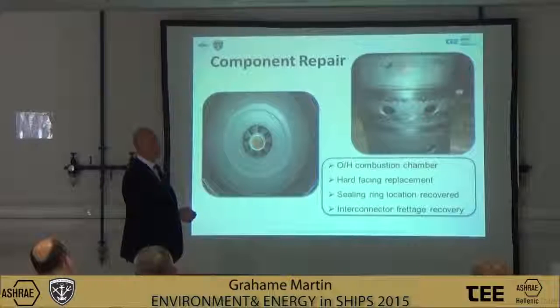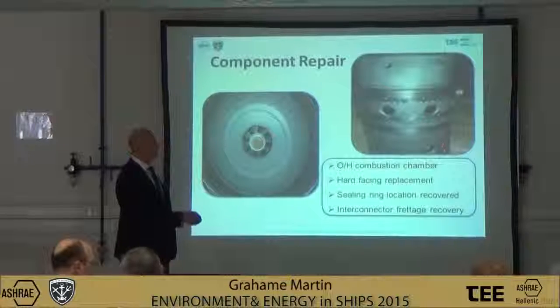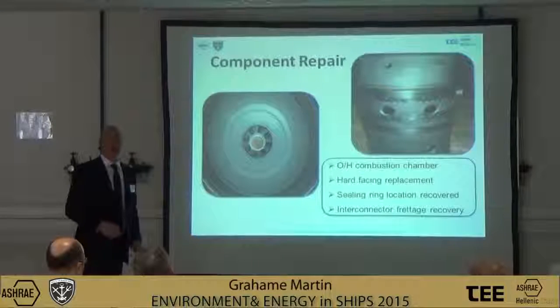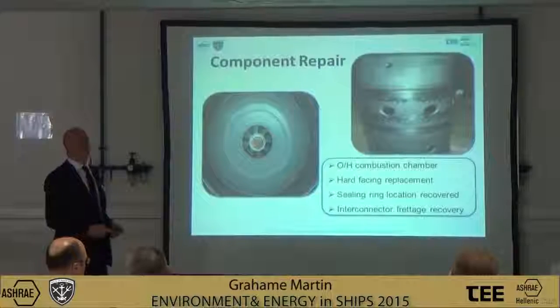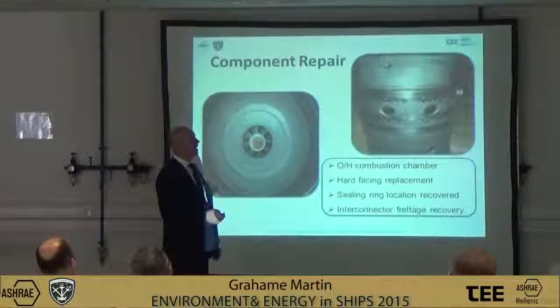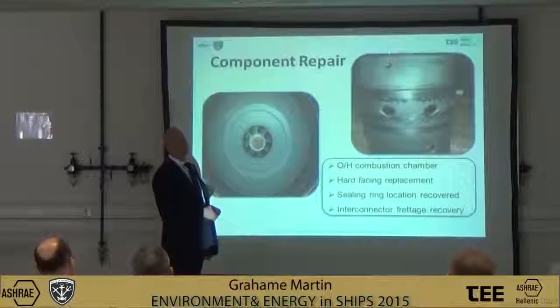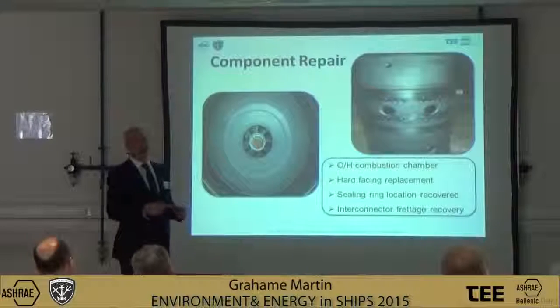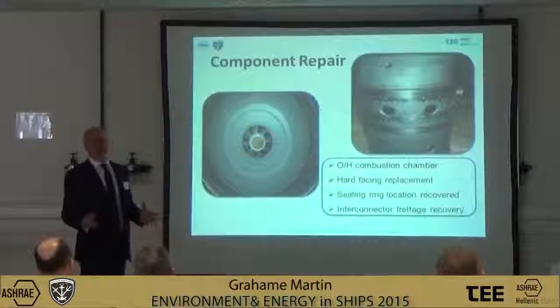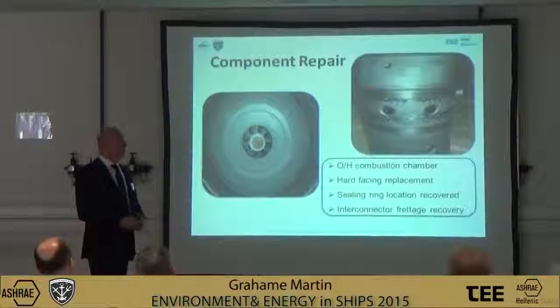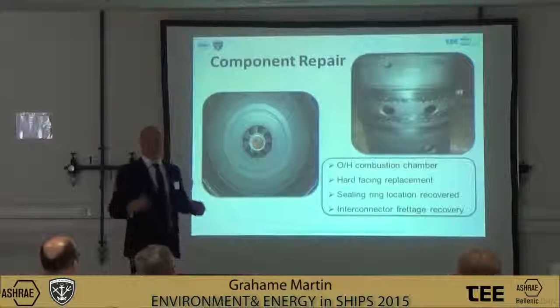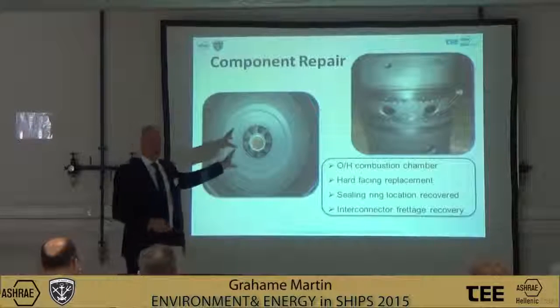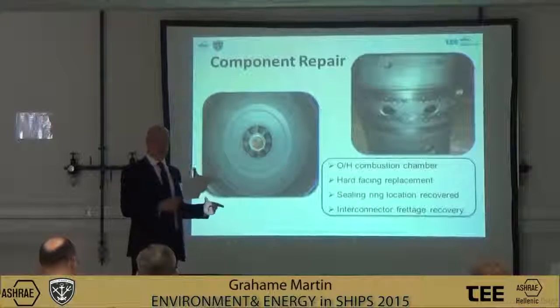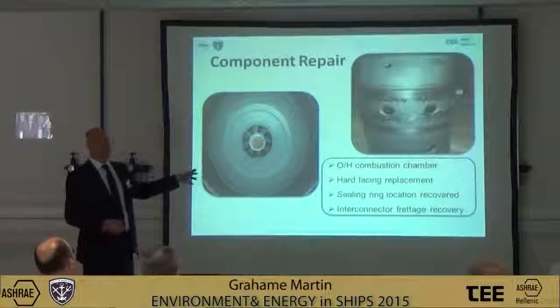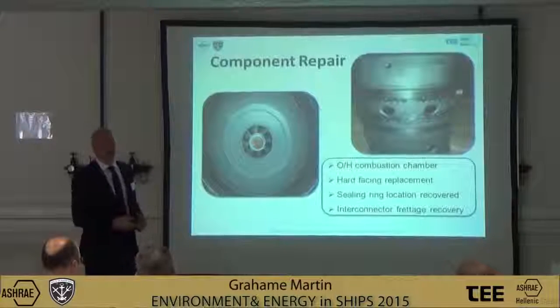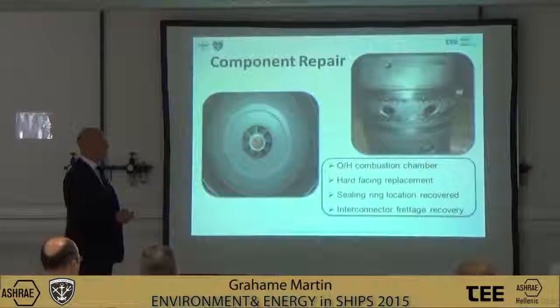Just on the forward, this is the forward end of the combustion chamber, and this is the rear section of the combustion chamber. We can also apply hard face coatings to these areas. So the air intakes now coming from the LP and HP compressors come into the forward end of the combustion chamber. There is a location there which unfortunately also wears, but we can recover that, again, with a hard facing. And the same at the rear of the combustion chamber, there are 2 half clamps that we saw in the other picture when the turbine section dog ring was being fitted. There are 2 half clamps that hold the rear of the combustion chamber in location. Again, we can recover that area by flame plating and machining back to tolerance.